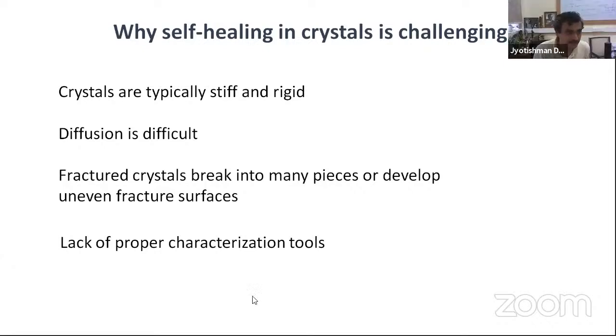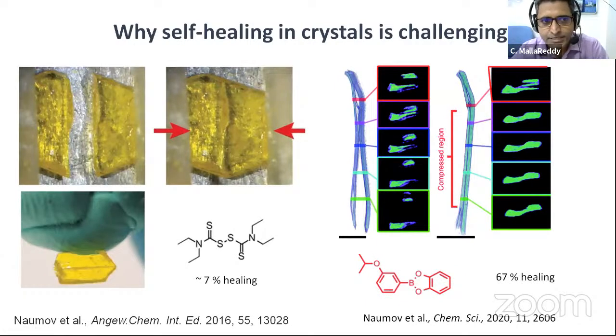Okay. Sure, that's perfect. So here then in organic crystals, other groups have shown, this is done by Panče Naumov from NYU Abu Dhabi. They have shown that if you take a crystal of this molecule, and then you break it into 2 pieces, you put them on 2 plates, and then you make a cut and pull them apart. You have a crack, then you put them together for 24 hours, and then there is a kind of healing. You still see a big crack here. So then when you pull them apart, you see that it is 7% healing.